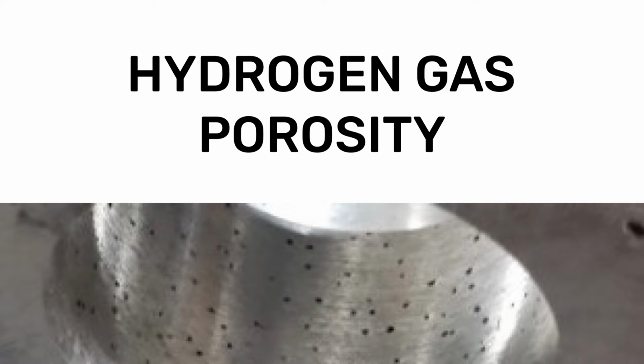And then the spindle spins around really fast, mixing in all the additives, and those additives combine with hydrogen and bring all the impurities to the surface. So at that point, all your operator has to do is scrape off these impurities and your aluminum's good to go. This really helps prevent hydrogen gas porosity defects.